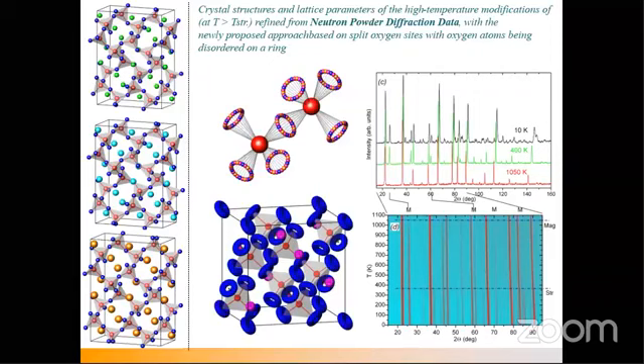So you can see that in order to refine the movement of the metal-oxygen-metal bond, we have clearly resolved the oxygen positions. In X-ray we cannot see these rings, these donuts. So we split the oxygen atomic position into 15 subatomic positions with an angle between neighboring positions of 24 degrees. So 24 times 15 is 360. We split the particular oxygen atomic coordinates which show these movements, and then refined the neutron powder diffractogram again. And then we were able to see these minute rotation mechanisms by neutron powder diffraction.